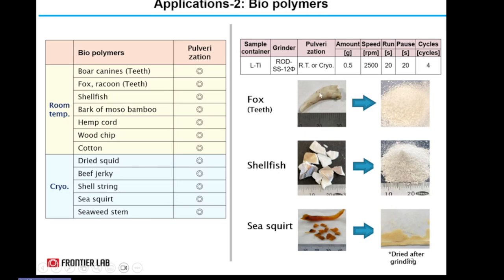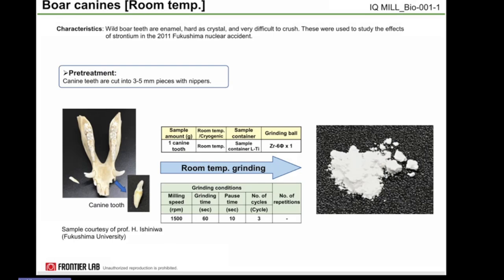So you can see the material before grinding and after grinding. Here, in some cases we have used cryo, and mostly the RPM is like 2500, 20 seconds, and up to 4 cycles. So again, cycles are not repetition, just 4 cycles within one repetition. So this boar canine is actually as hard as crystal. People have used it for studying the nuclear accident effect, for strontium analysis, aging purposes.